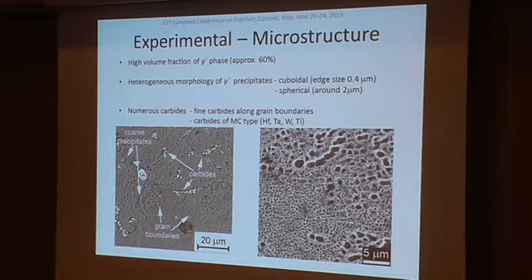This material is characteristic for the strengthening phase gamma prime. In our case, we had approximately 60% of volume fraction. We had 2 types of precipitates in the material, cuboidal ones with edge size about 400 nanometers, and spherical ones with diameter of 2 micrometers. And also we had in the microstructure numerous carbides along the grain boundaries, and carbides of MC type in interdendritic areas.